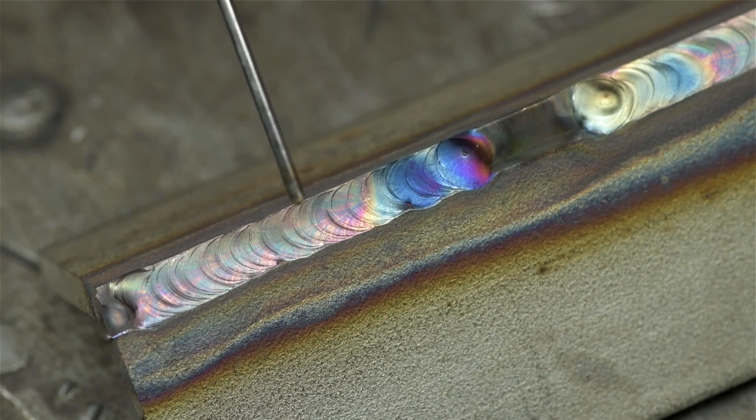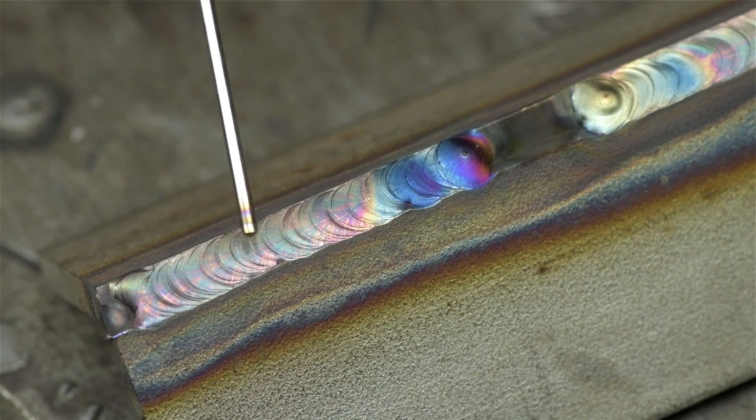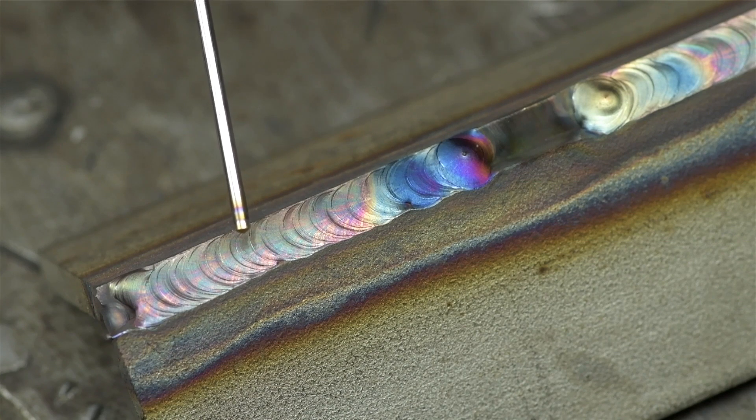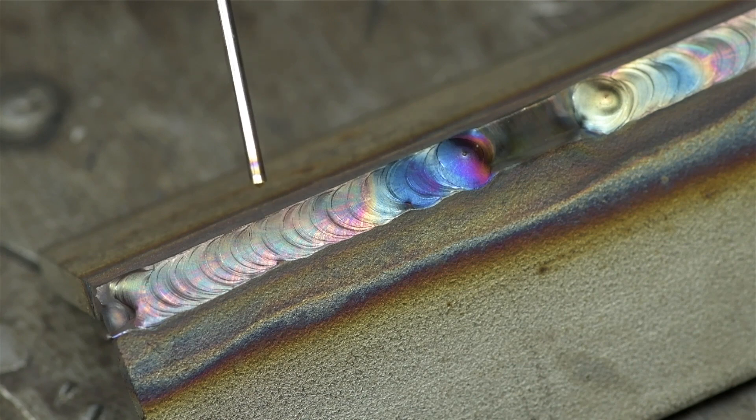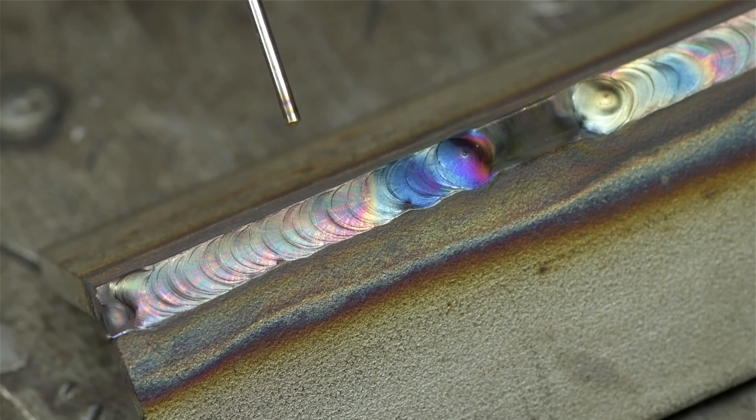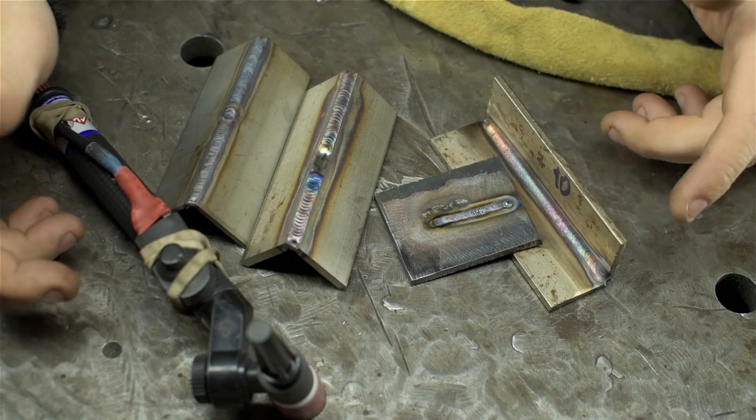But too much gas can do two things. First, it wastes a heck of a lot of gas. Gas costs money. Now if money is no object and you like hearing your torch hiss like a banshee, the other downside is that that fast of a flow rate can suck atmosphere in along with the argon. Instead of covering and protecting your weld, the gas is sort of pressure washing the whole area, pulling in air, and again potentially contaminating your weld.